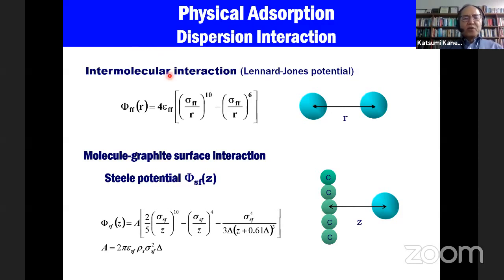Ordinarily, we use very simple approximations. At first, if we have two atoms or two molecules, at some so-so distance they attract each other, but if they approach too much, the electron waves overlap and it becomes repulsive. Then the Lennard-Jones potential, as shown here, describes such repulsive and attractive situations. This attractive force comes from the so-called van der Waals attractive force, the dispersion interactions.